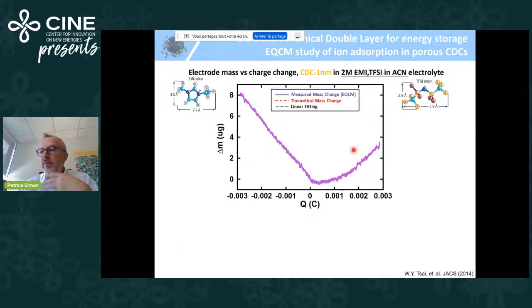Same applies when you start from open circuit potential to positive potential. So you have a capacitive-like signature with a weight change, a frequency change, of a quartz corresponding to a weight change because anions and cations are going in and out during the polarization. From this cyclic voltammetry, you can calculate the charge, and then you can transform the frequency in weight change, and then you can plot the weight change of the electrode versus the charge.